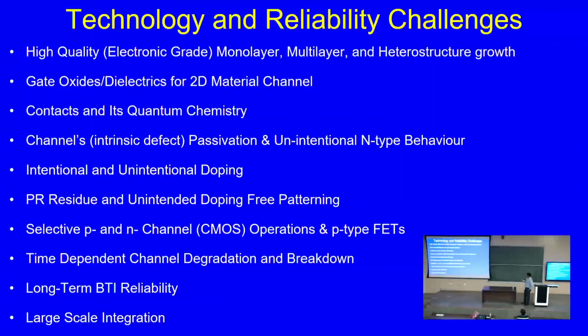We wrote a paper on that, which is also a reason for the hysteresis shown in 2D material based transistors. So how to make these transistors intrinsic, passivate these defects, or undo this unintentional n-type behavior, right? Then how to dope these 2D materials intentionally, how to build the process without having the PR residue sticking on it. So what happens is these 2D materials are just 1 atom thick. Now any process that you do, you will use photoresist. The photoresist sometimes has affinity towards surfaces, and if you don't have a proper well-defined process, the PR would stick to the 2D material, and sometimes the PR can also take out the 2D material, leading to damages, right? So how to build a process which is PR residue free.